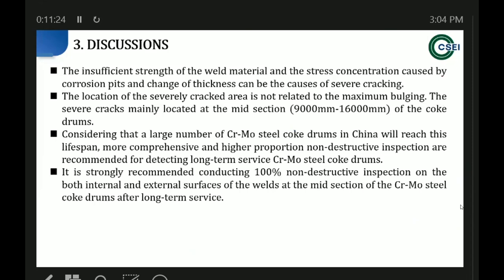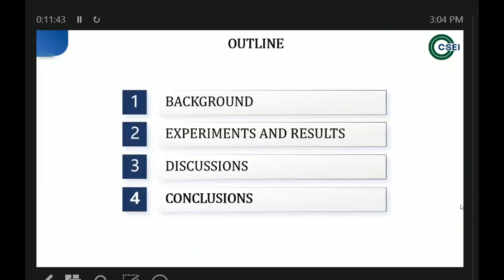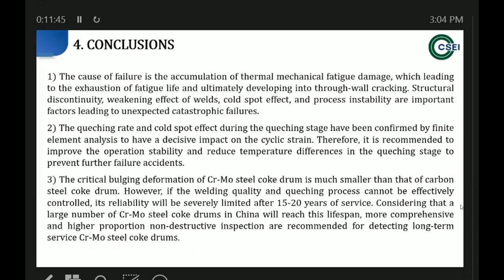So based on these results, we strongly recommend conducting 100% non-destructive inspection on both external and internal surfaces of the welds at the mid section of these coke drums during long-term service. It should start after 15 years of service, I think. So that is the conclusion. We concluded the reason for the failure and gave suggestions for the operation, and also suggestions for inspection.